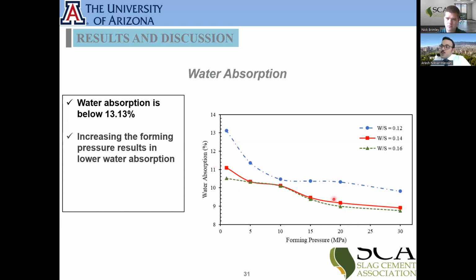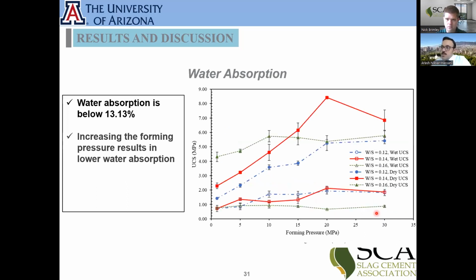Then after water absorption, when the samples are wet, we take them out and test them for the UCS. And also we let those samples dry and then test them again. And this graph shows you the results. So these 3 graphs on the lower side are for the samples that we take out in a wet, saturated condition and just test for the UCS. And then we let them dry for 24 hours at 90 degrees Celsius. And then we test them again and see which samples are more durable when we are exposing them to the water.